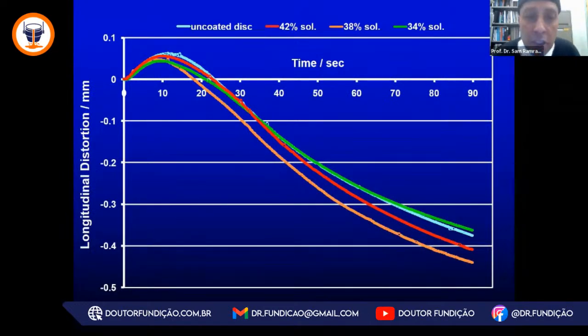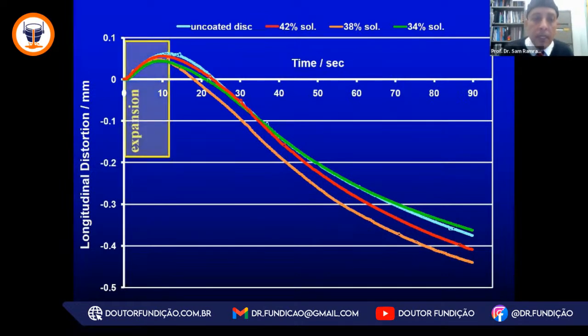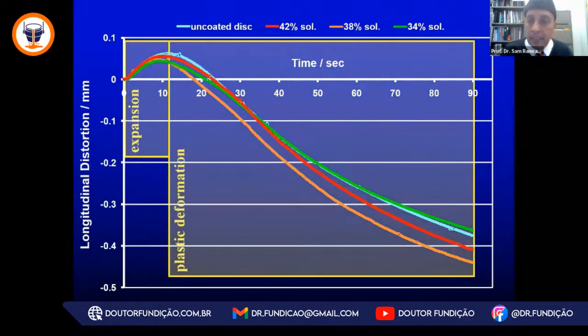So we have to engineer these coatings. They can prevent the veining and penetration. But right now, if we don't choose the coating correctly, they will not prevent distortion. And here we are seeing whether we coat or we don't coat, there is no difference for expansion and plastic deformation for the sand binder systems.